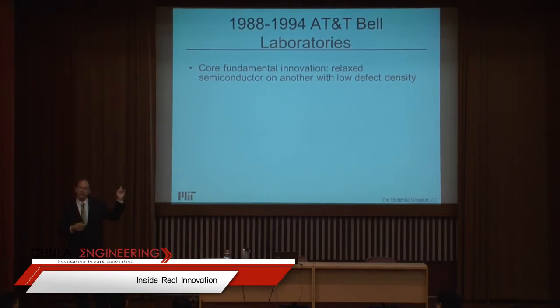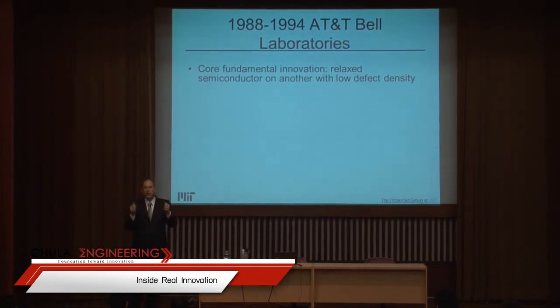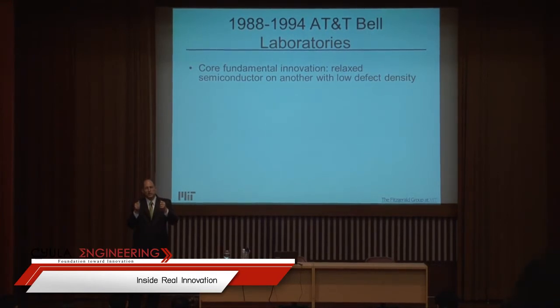So what do we have? Well, the gallium arsenide was good quality back then, but it wasn't as good as I showed you here. But we could go part way, and we could make relaxed silicon germanium, like with 30% germanium, really high quality. And so we said, what can we do with that, right? What you could do with that is, remember how I said we can induce lots of strain? Well, if you have a bigger lattice constant and now you deposit a thin layer of silicon on top, it tries to line up with the larger silicon germanium lattice. And so you can make a thin layer of silicon that has a gigapascal of stress in it, right? And a gigapascal of stress is enough to make the band structure of silicon change, and you get really high mobility carriers, right?